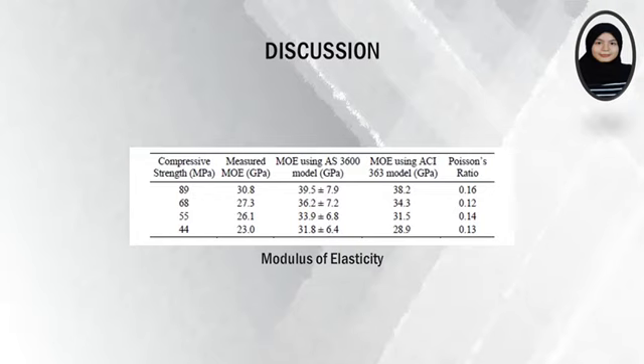Lastly, Hardjito and Rangan reported that the modulus of elasticity and Poisson's ratio of fly ash-based geopolymer concrete were of the same characteristics as those of OPC concrete. Also, the measured stress-strain relationship of geopolymer concrete fit well with the equation designed for Portland cement concrete. The measured values of the modulus of elasticity of geopolymer concrete with compressive strength in the range of 44 to 89 MPa were similar to those of OPC concrete, yet the measured values were at the lower end of the values calculated using the current design standard, as shown in the table.